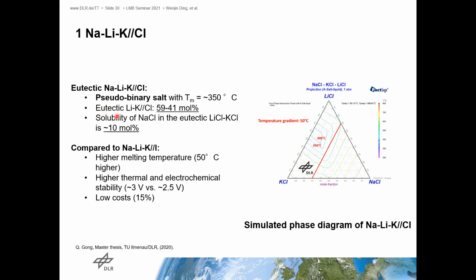The sodium chloride is dissolved in the eutectic lithium and potassium chloride salt mixture, and its solubility is about 10 mole% from the simulation. But compared to iodide salt, it has higher thermal and electrochemical stability and lower cost.